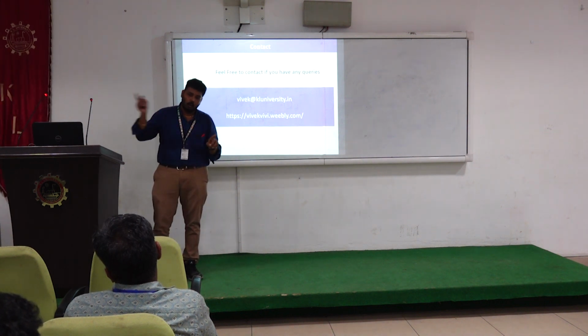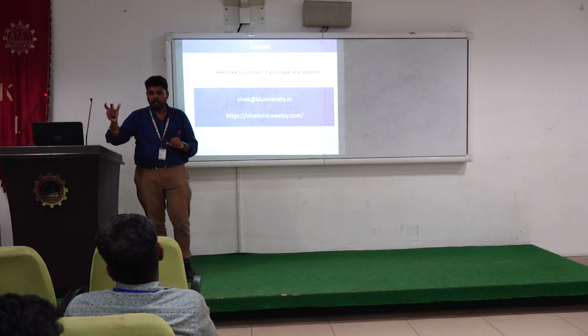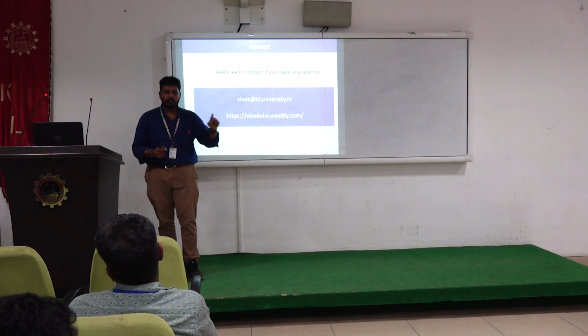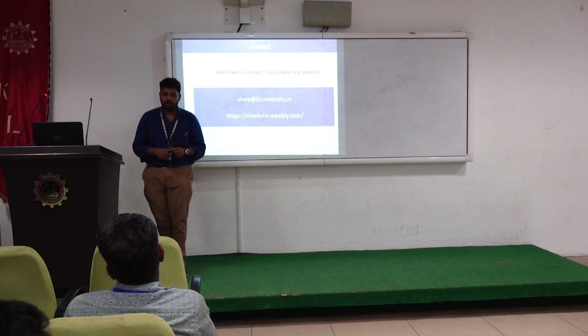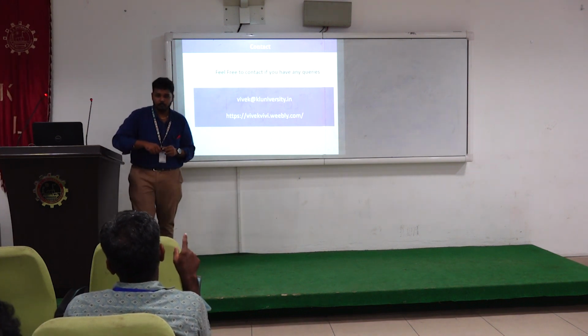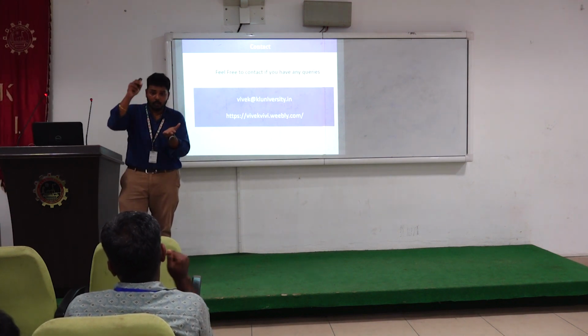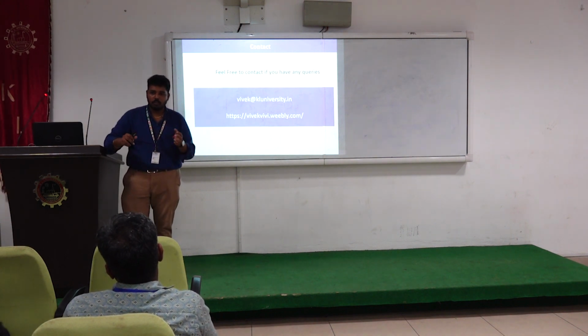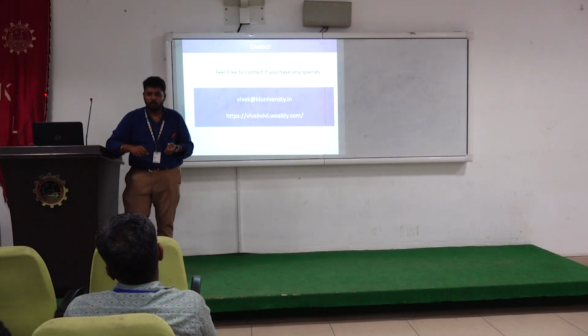Then we have to go for a doping approach. So enhancing the piezoelectric coefficient is one way to get a high performance device, and identifying a better dielectric material will lead to a triboelectric nanogenerator with high performance. For measurement of the piezoelectric coefficient, which one will you consider? D33, because we are going for vertical contact and separation, right? So D33 mode is better. If you are going for stretching, then D31 mode would be better.